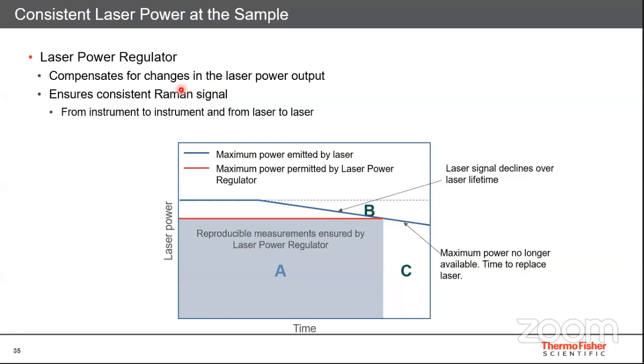It compensates the changes of laser power output. So what normally happens is that over a period of time, with the use of the instrument, the laser light falls, it goes down and down. But when you're doing an analysis, you always want the same amount of light to fall upon the sample. So if you're doing an analysis for your sample with a particular amount of laser light to get your result, next time, even after a year, you want the same amount to fall upon your sample so that you can get a consistent result.